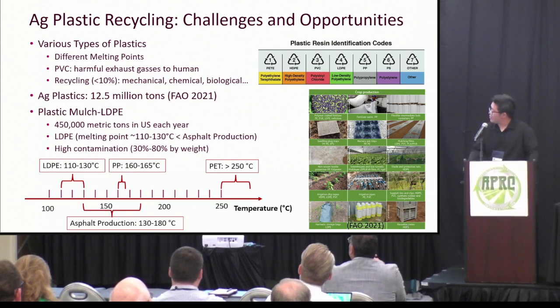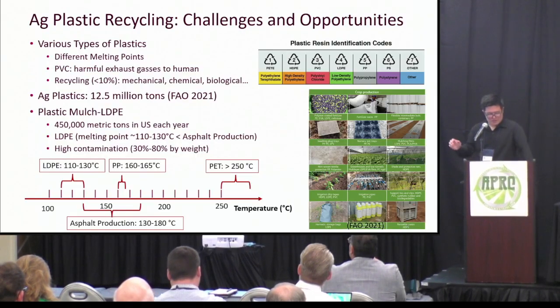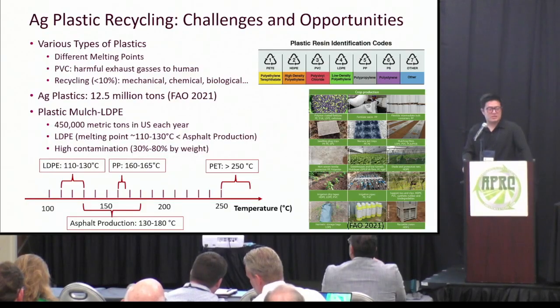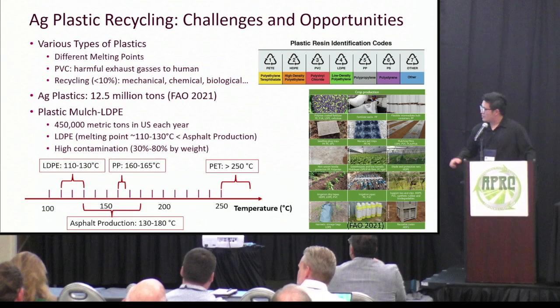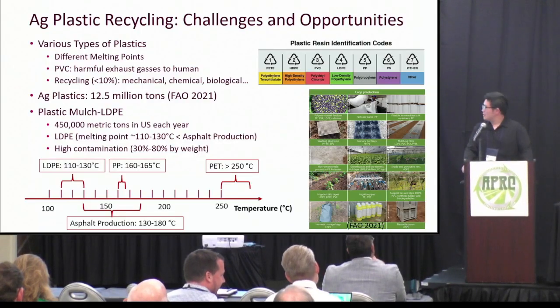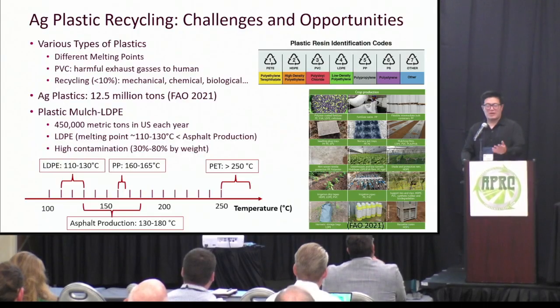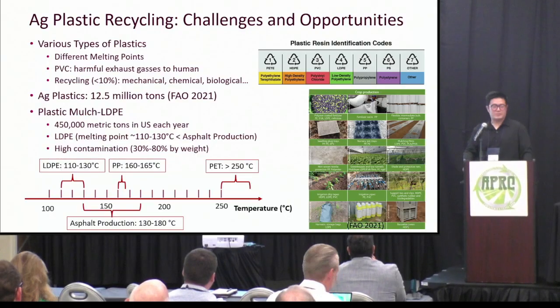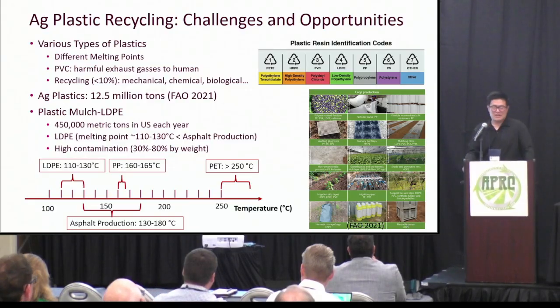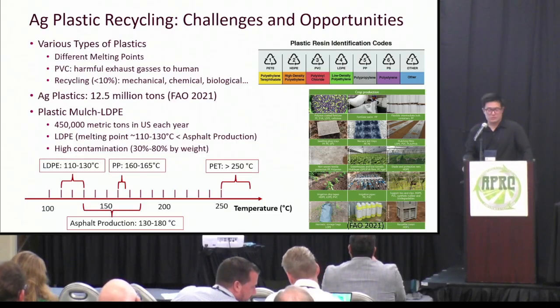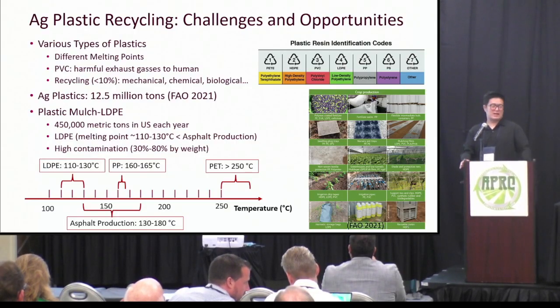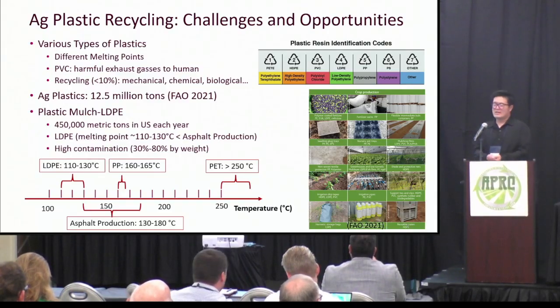And if you look at plastic mulch here, in the US each year there are 450,000 tons. And the plastic mulch is made from LDPE, so the melting point is between 110 to 130. It's lower than the asphalt production temperature, which is around 130 to 180. So that is very good news. The mulch can be melted into the asphalt or modified asphalt during asphalt production. But for the downside, the mulch waste has a very high contamination level, around 30% to 80% by weight. But maybe the asphalt can have a higher tolerance to accommodate this very high contamination level.